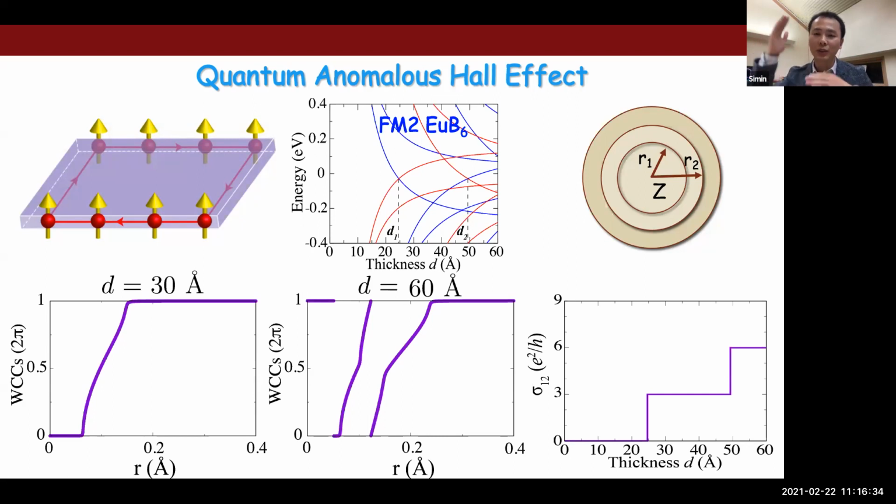But if you apply a quantization in one direction, here I use the z direction, in this material, for the same field the situation becomes different. So you can reach a very large Chern number, whatever it can be, but it must be a multiple of 3. And the multiples of 3 is why again? Can you tell me? Is it because there are 3 copies? Yeah, because there are three pair copies of Weyl points.